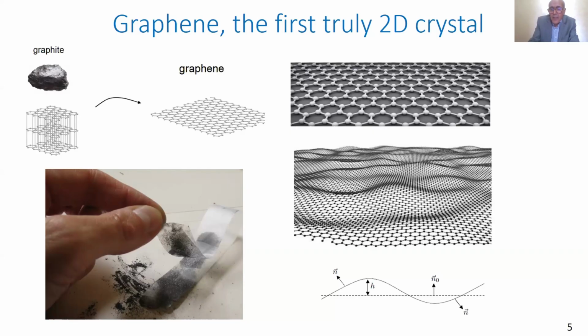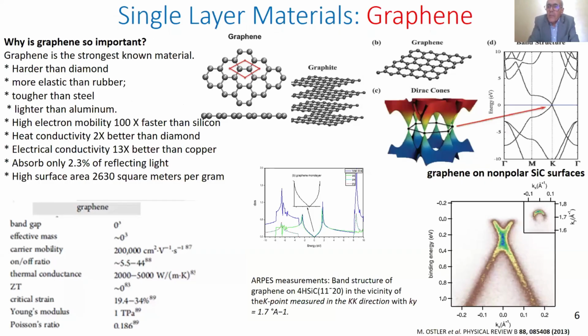This material has been obtained, as I show experimentally, but has been studied extensively, theoretically and numerically, and many important and unique properties have been shown. The first thing is that graphene is the strongest known material, harder than diamond, more elastic than rubber, tougher than steel, lighter than aluminum, high electron mobility 100 times faster than silicon, heat conductivity two times better than diamond, and also high surface area, more than 2,600 square meters per gram.